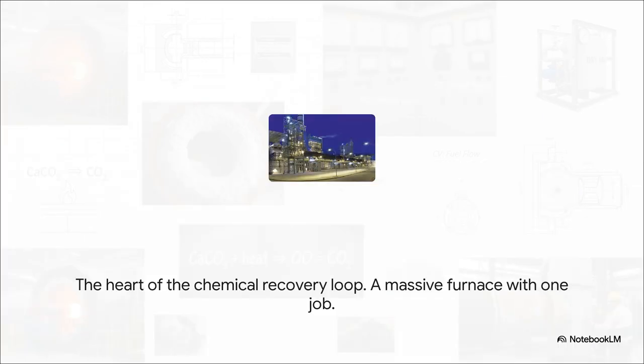So what you're looking at here, this massive rotating furnace, it has one and only one critical job. It takes the spent lime mud and cooks it, regenerating it back into active calcium oxide, what we call CaO. And that CaO, that's the chemical that drives the entire kraft pulping process. If you don't have CaO, you're not making pulp. It is literally that simple.